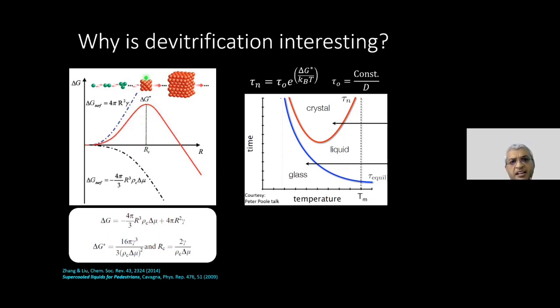And once you cross this barrier, you're essentially going to form a crystal, and the surface tension is going to ensure that you try to form a compact crystal. Okay, that's when you pay the least penalty, right? Now you can do some trivial algebra and find out the size of this critical nucleus, and that turns out to be a parameter that depends both on the surface tension and this delta mu. The delta mu is basically the difference in chemical potential between the parent phase and the product phase. And you can also find out what the delta G star is, which is the height of this barrier that you have to cross.